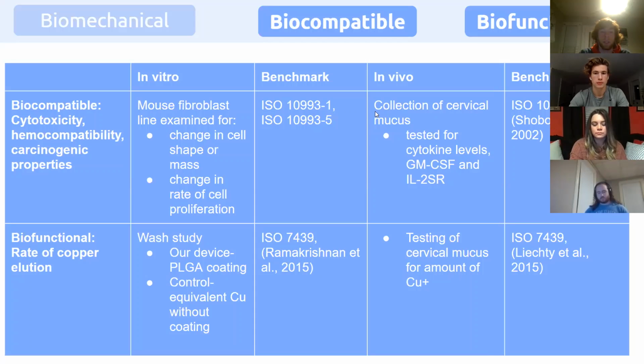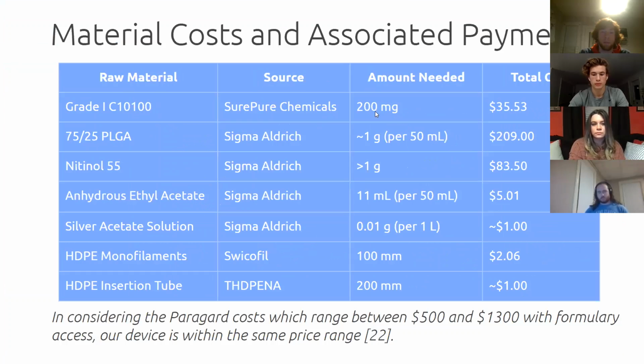We will also seek to determine the rate of copper elution from our device. We will do this using a wash study that includes our device with its PLGA coating and a device with an equivalent amount of copper without the PLGA coating. For our in vivo study, we will test the cervical mucus in order to determine the amount of copper that is eluted from our device.